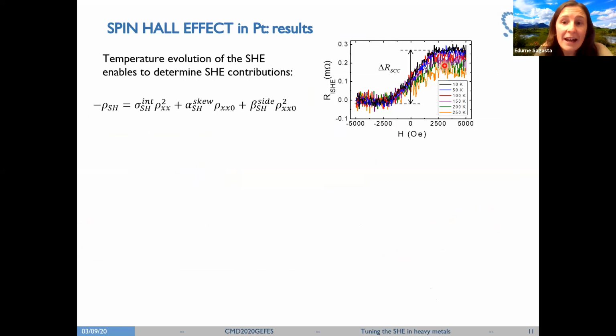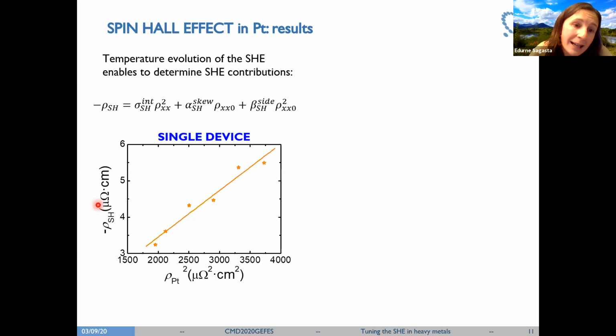So in the end, what we are able to do is plot the spin Hall resistivity value, because we extract it from the spin Hall angle, as a function of the square of the platinum resistivity, because we know which resistivity of platinum corresponds to each temperature. I'm plotting as a function of the square of the resistivity because, considering the phenomenological equation, the slope will give us the intrinsic spin Hall conductivity, and the intercept will give us information on the extrinsic contribution. In fact, in platinum, it was demonstrated, or it can be argued, that the side-jump contribution is negligible.